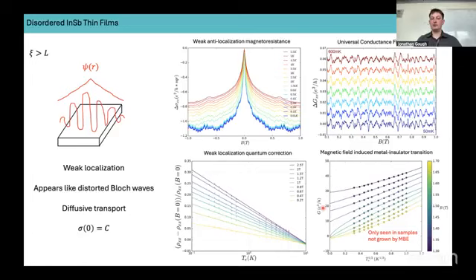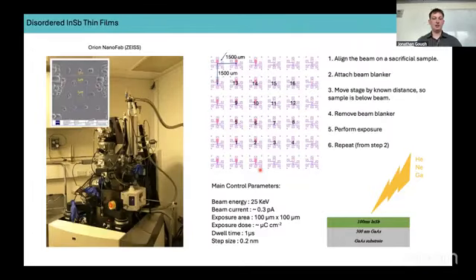So to enter this strongly localized regime, we developed this ion damage procedure. Typically an ion beam or a focused ion beam is used for imaging. They're very complicated bits of equipment, but if you characterize the beam correctly, you can resolve 20 to 30 nanometer features. So originally we were imaging our devices with a focused ion beam. Here's an example of an anti-dot array. But what we noticed was if we looked at a sample for more than a few seconds, they became unmeasurable at low temperatures, which obviously wasn't ideal. So we took advantage of this and developed this ion damage procedure, because it was clear that the ion beam was disordering our typically very clean semiconductors.